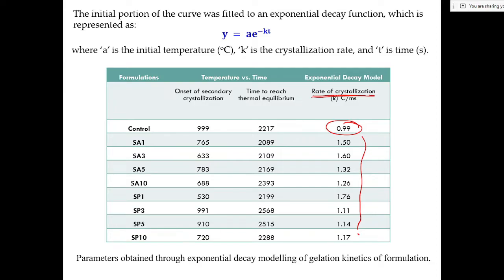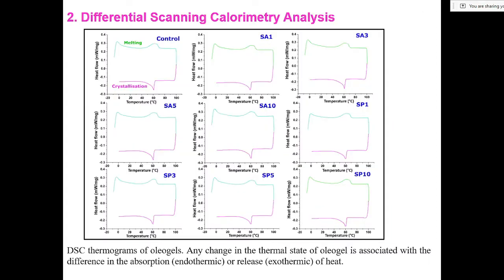Okay, again if you look over here, it was 1.50, then at SA3 it increased, then it started decreasing. In the Span 60 based oleogels, we had the highest rate of crystallization. After that it reduced to the lowest, and it remained in this range for the rest of the samples. Okay, so you can see how the emulsifiers, even when we have added them in a very low concentration, affect the properties of the samples. Okay, then we performed the DSC analysis, which is the thermal analysis.